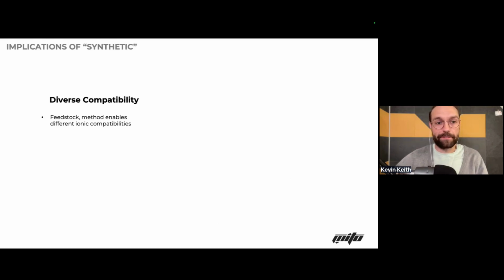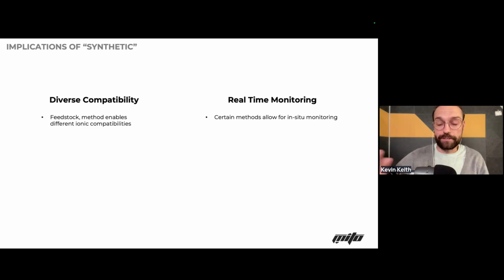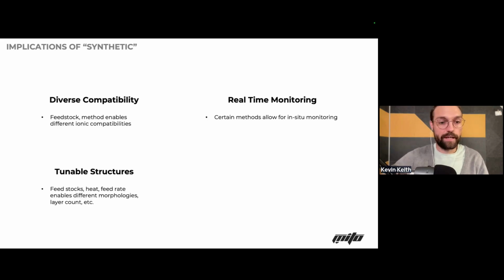The feedstocks and method enable different ionic compatibilities, and you can actually have real-time monitoring. As it's going through this pyrolysis or plasma method, you can have in situ monitoring, where you can take real-time readings of layer count, crystallinity, carbon content, so you know in real time if you're hitting your QA/QC. That way you don't have to make a batch, go back to the bench top, run it through, and spend more time doing it that way. So you can dial in what is going on in real time. With that dialing in, you can fine-tune the structures.